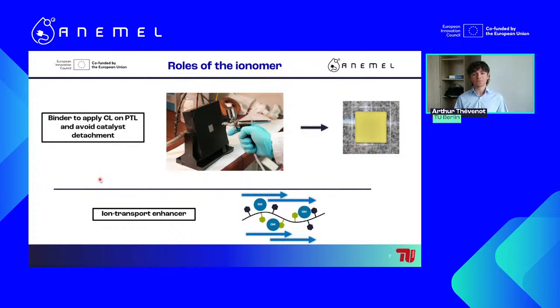Well, our powder catalyst will be mixed with the solvent and with the ionomer, and that will give us what we call an ink. This ink will go in this airbrush, as we see here, and we will simply hand spray it on our PTL that is right here. And yes, it's the exact same airbrush that you would use for art purposes, such as painting miniatures, in case you are into it. After the spraying, we obtain this electrode, this anode in this specific case. The bright yellow color that you see over here is the catalyst layer that is typical of the nickel-iron LDH catalyst before its electrochemical activation. Once you activate it in your system, it becomes fully black.